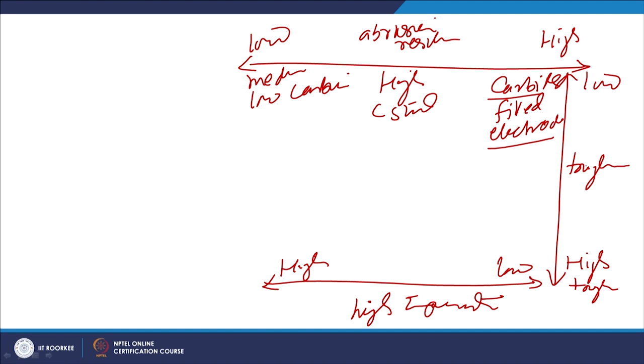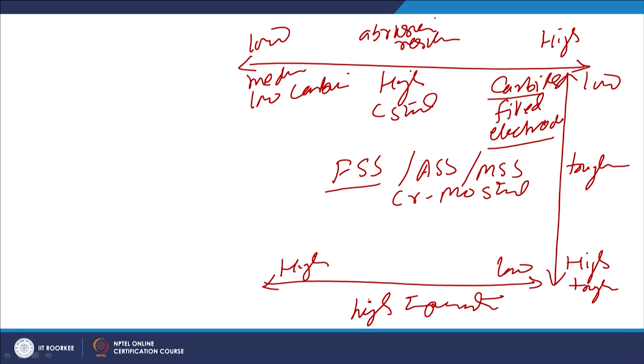On the other hand, for a good combination of the toughness as well as the high temperature resistance, we will have the ferritic stainless steel and austenitic stainless steel, martensitic stainless steel, chromium molybdenum steels, and for high temperature, nickel and cobalt base alloys. So this is the category where they have high toughness as well as high temperature resistance.